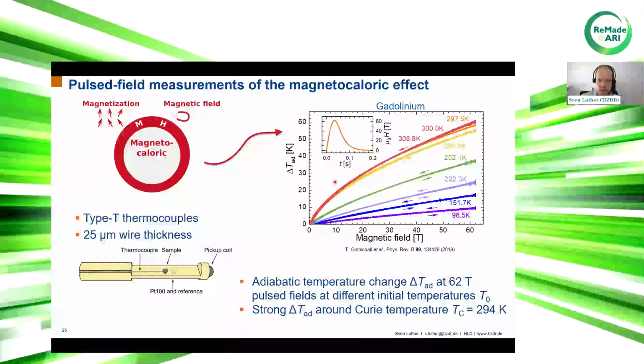So here I want to present now the measurements of the magnetocaloric effect on this benchmark material gadolinium. This was measured in high magnetic fields up to 62 Tesla at different initial temperatures. You can see here that this material has the Curie temperature, or phase transition, at 294 Kelvin. That is why we have a high magnetocaloric effect at the phase transition, where we have a high temperature change of up to about 60 Kelvin.